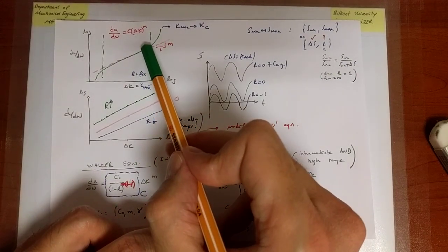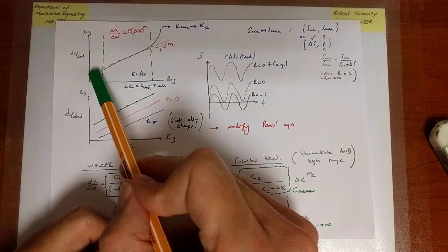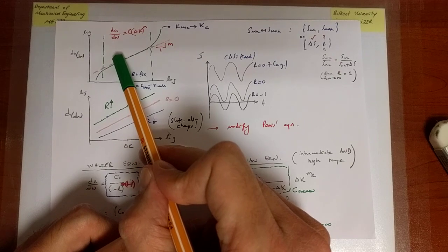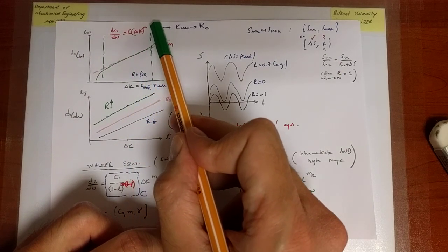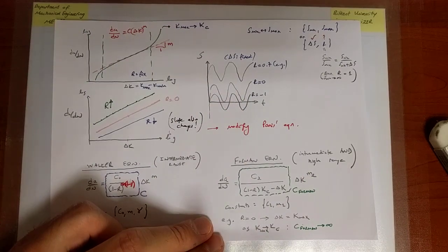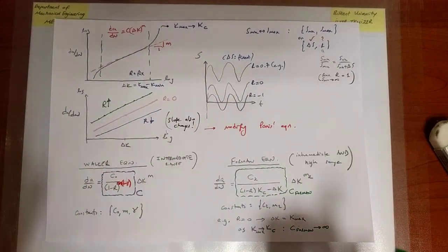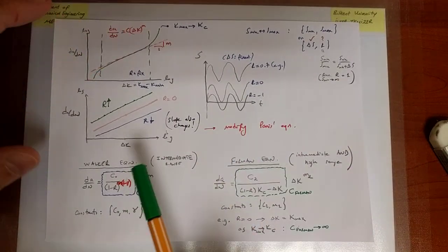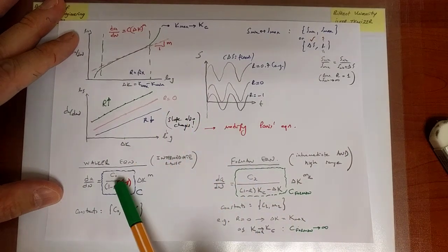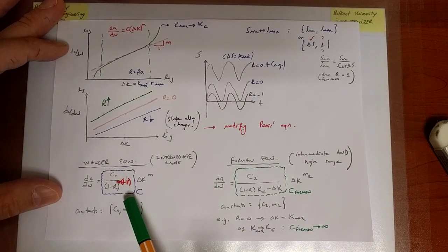And that's going to eventually cause this curving up behavior. It will also cause a slight deviation from this line in the intermediate region, but the extent of deviation will become more and more prominent as you approach the fracture scenario. So therefore, what we've done is we've started with the Paris equation, then we've generalized it towards Walker in order to incorporate the influence of the stress ratio.